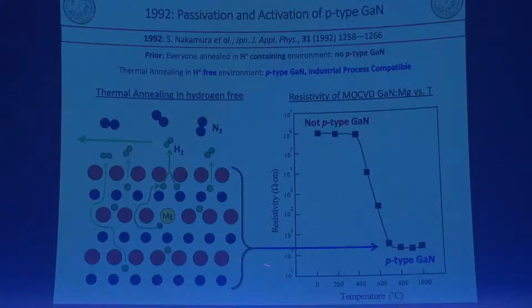So for the p-type layer, usually people dope magnesium to get the p-type layer, but after doping magnesium into gallium nitride, it is always resistive, semi-insulating. But in my case, just doing thermal annealing, we got low-resistivity p-type gallium nitride. Also, at the same time, I clarified the mechanism, why we got p-type gallium nitride. Hydrogen passivated the magnesium acceptors, and using thermal annealing, we can remove the hydrogen. This is called hydrogen passivation.